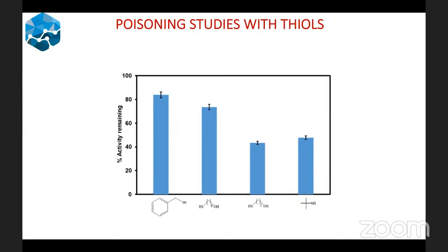So as you can see here, we used these thiols, and this is the activity of your catalyst. This is a bulky thiol, as you can see. You can see that the yield that we obtained when you use this thiol is very high, simply because this compound is not able to move into the pores of the MOF, right? It remains outside. Therefore, it cannot poison our catalyst. So our catalyst remains very active.